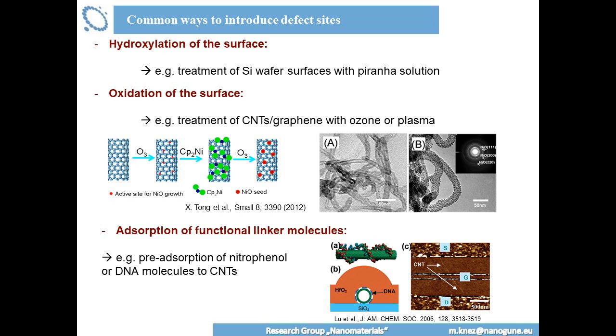It's fascinating. It's a bit tricky, but here you can do, let's say, a little bit more non-regular ALD. In ALD, you usually want to coat the whole surface. Here you have the possibility to functionalize sites of the surface and to do area selective ALD, not in terms of industrial area selective, as Paul showed yesterday, but I mean spot-defined area selective ALD. You will not be able to define exactly where the spot is, where a particle grows, but you will have a high surface area, for example, for catalysts. This is a real thing.